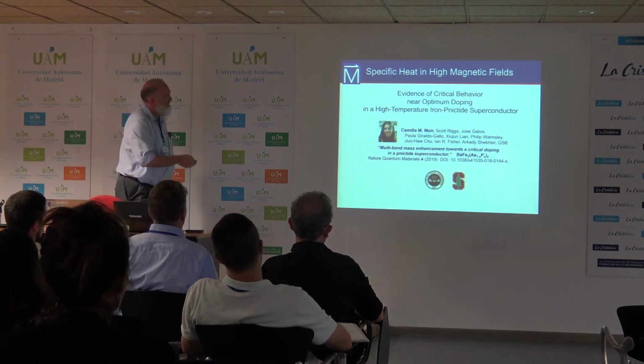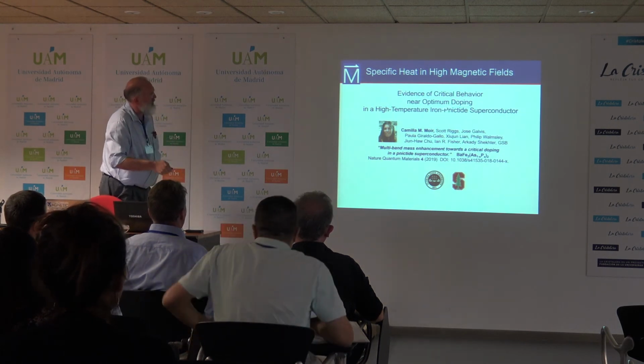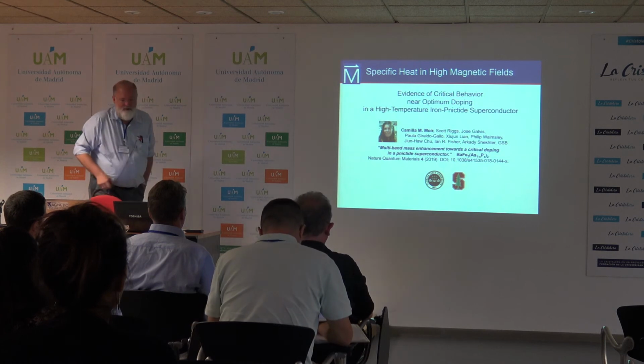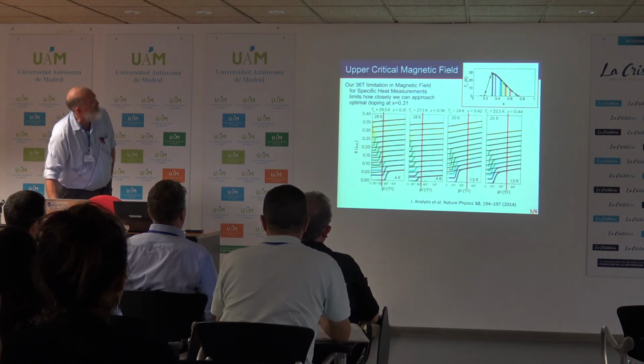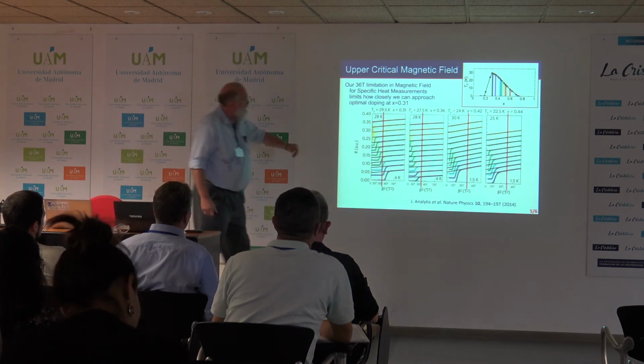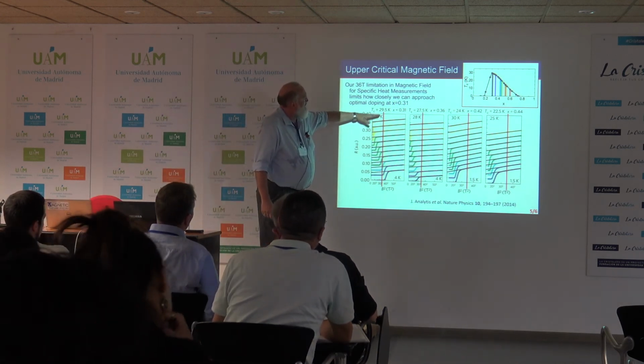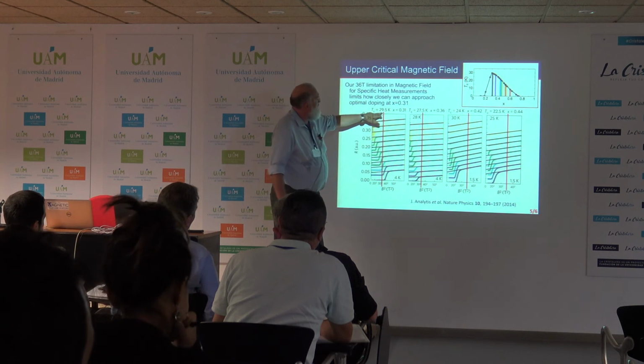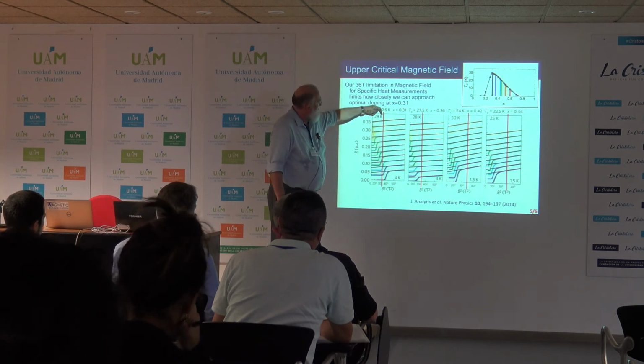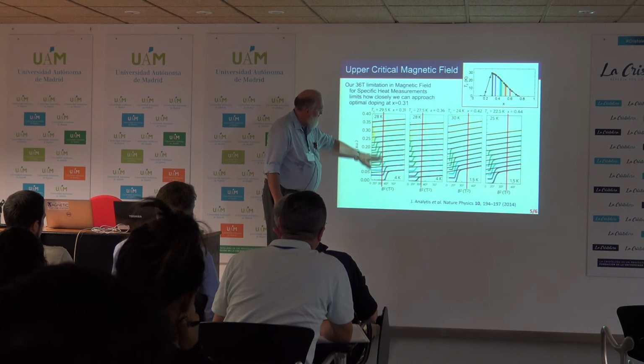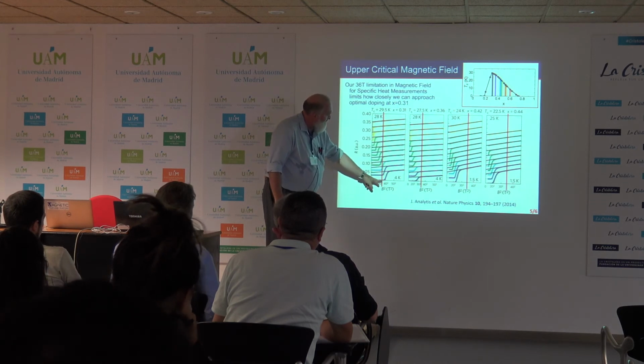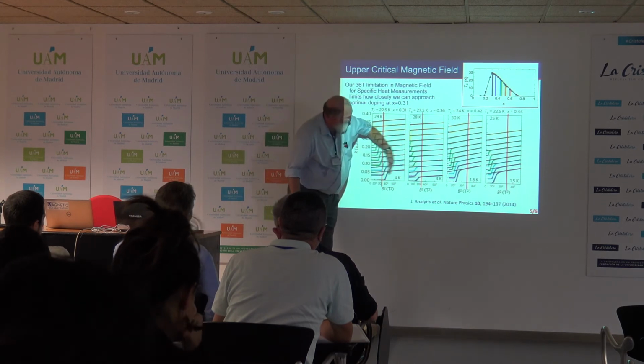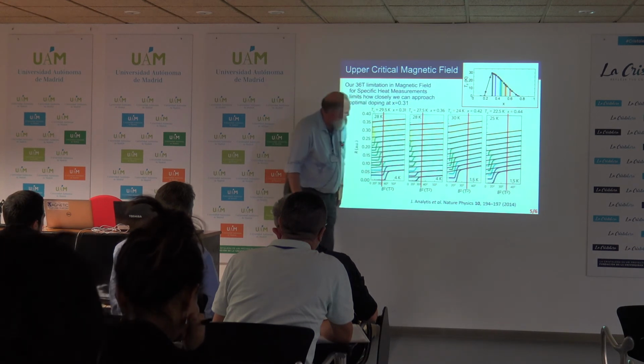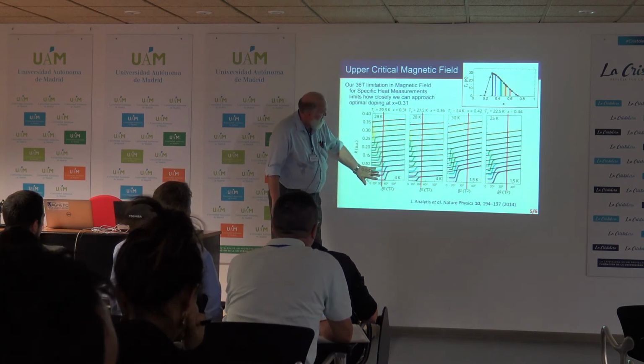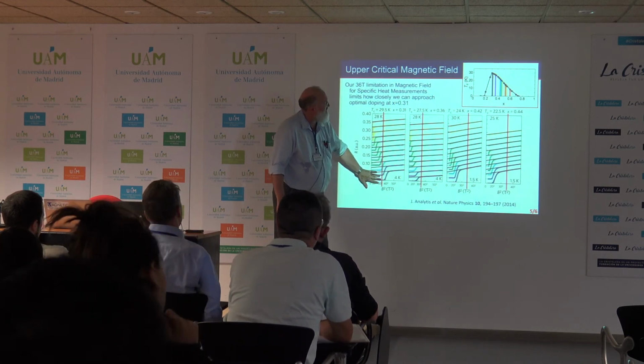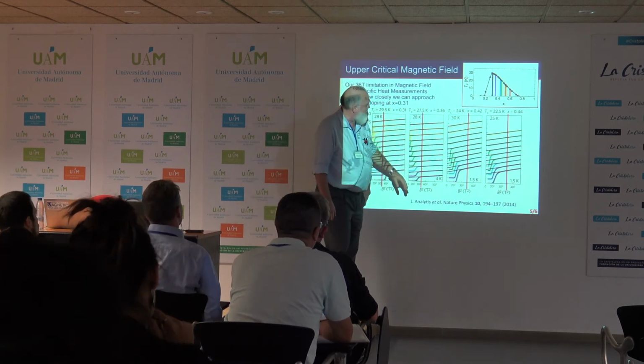So what Camilla and the rest of my group was working on was specific heat in this system. And these are data from James Analytis just to illustrate that for the higher TC system, 29 Kelvin near optimum doping, we cannot go down to arbitrarily low temperatures because our magnetic field is limited to 35 Tesla, so we're not able to measure any of this regime. And so, at least near optimum doping, we're stuck looking at a superconductor. We're not able to measure the specific heat of the normal state.